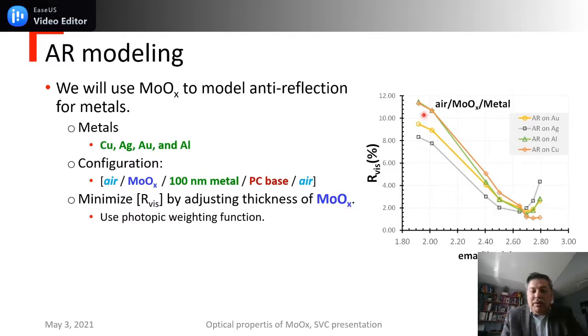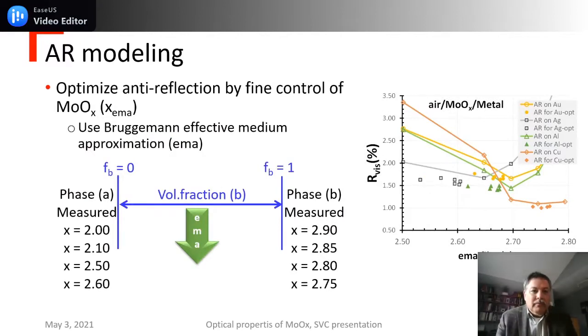And we can see for many metals, reflection starts out between 8 and 12% for low levels of oxygen, and a minimum is at a stoichiometry of around 2.7. Well, we don't have to just depend on the target stoichiometry. We can make finer control and optimize the anti-reflection by using the Bruggeman method. We can start in phase A with a number of different stoichiometries, phase B with stoichiometries of 2.9, 2.85, and so on. We can vary the volume fraction and see what happens. And now we can see that for copper, we're down around the 1% level.